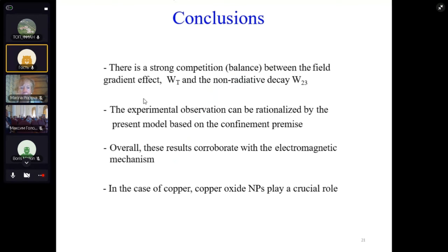And so, concluding, it's very important, as I have shown in the first energy level diagram, showing the plasmon band in a general way and the energy level scheme of the emitting species, that there is a competition or a balance that should be taken into account between field gradient effects or local field enhancement, non-radiative energy transfer from the emitting species to the metallic nanoparticles if they are not oxidized, like in the case of silver or gold, and non-radiative decays inside the emitting species. This competition is very important to be taken into account when we set up an appropriate system of rate equations.